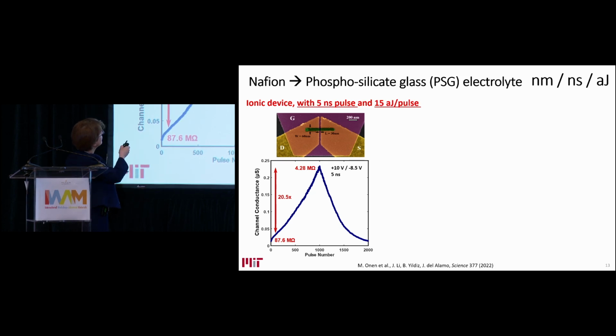And we could scale this down to about tens of nanometers, so 30 nanometer channel width, each functional layer 10 nanometer thick. And in this miniaturized device, we could again obtain more than an order of magnitude change in conductance, which is consistent with what's desirable. And we could push it down to nanosecond programming speeds. So 5 nanosecond was our limit.